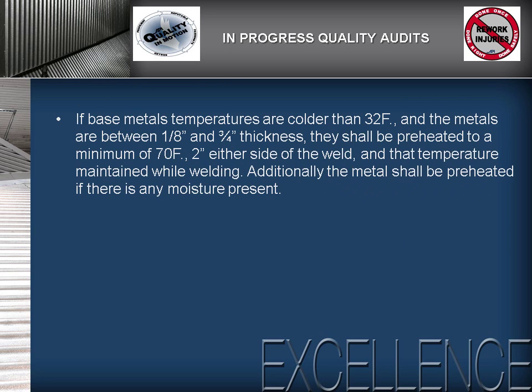General preheat requirements are as follows. If base metal temperatures are colder than 32 degrees Fahrenheit, and the metals are between 1/8 inch and 3/4 inch thickness, they shall be preheated to a minimum of 70 degrees Fahrenheit, 2 inches either side of the weld, and that temperature maintained while welding. Additionally, the metal shall be preheated if there is any moisture present.